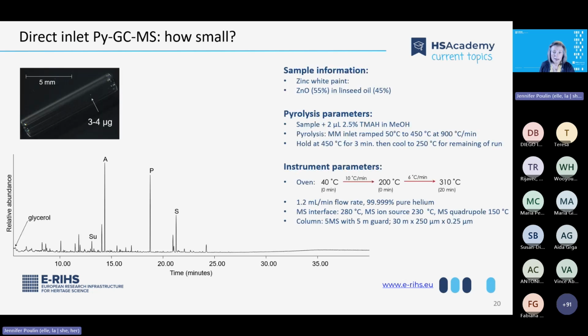For PyGCMS, I'll use just a few micrograms, and it looks like this in the sample tube. This is a zinc white oil paint. Here's the chromatogram that I actually obtained from that speck, derivatized with TMAH and pyrolyzed at 450 degrees Celsius. It was run in splitless mode, and it shows some excellent signal to noise. I wanted to show that very small sample size is now an option for PyGCMS.